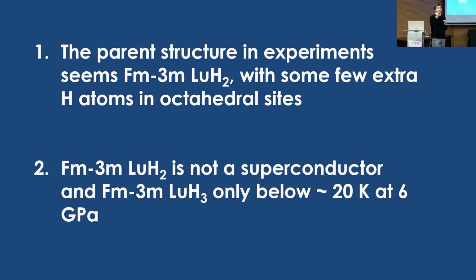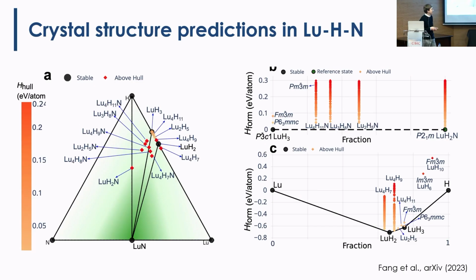But maybe you need some hydrogens in the octahedral sites to explain the Raman, this other peak at 250 centimeters minus 1. We obviously calculated superconductivity in these materials. Lutetium H2, 0, no superconductivity. The one that explains the color, there is no superconductivity there. And the other one, lutetium H3, yeah, 20 Kelvin at 6 GPa. Nothing compared to ambient pressure, right? So we said, okay, maybe there is something that we are missing.